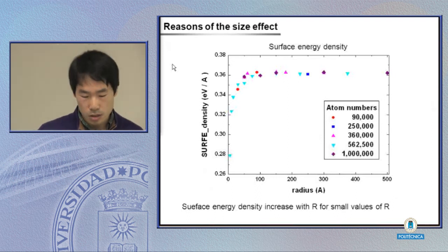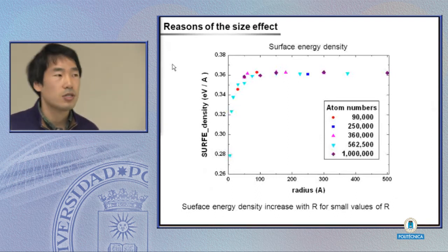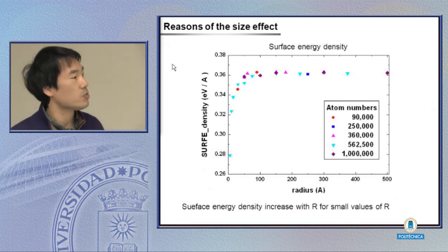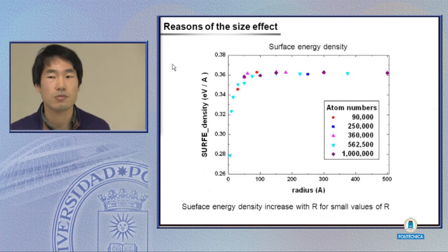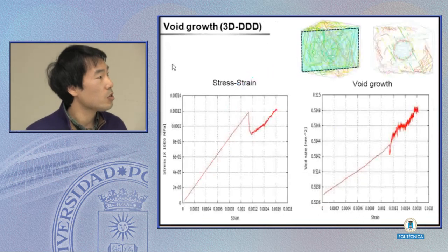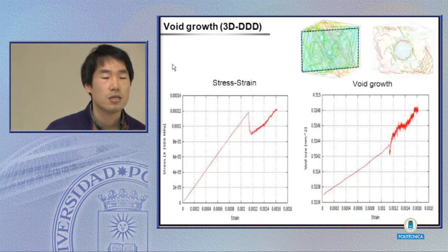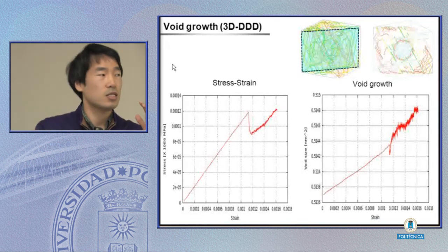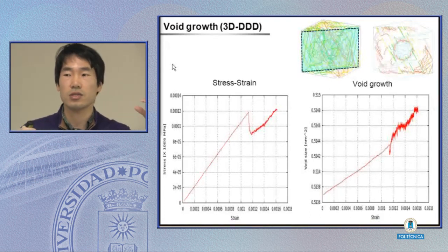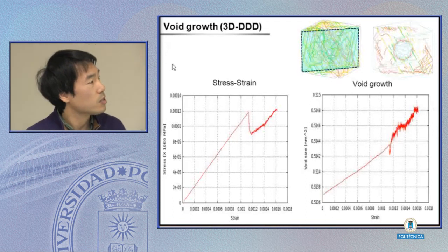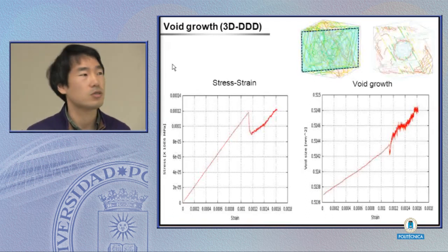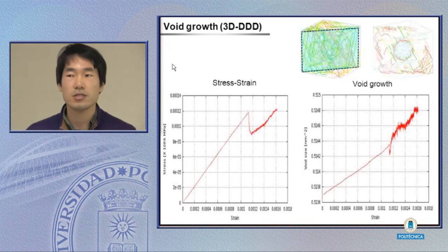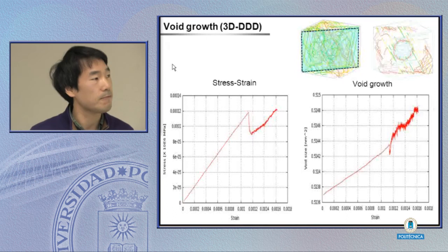The reason is the surface energies. As you can see, the surface energy is very low at the smaller void, and it increases very fast as soon as the void is more than 100 angstrom, and then it keeps constant with the void radius. The smaller surface energy means that when the void is increasing, it needs much smaller energy to make the increased surface. So it helps faster void growth. The lower surface energies help faster void growth.